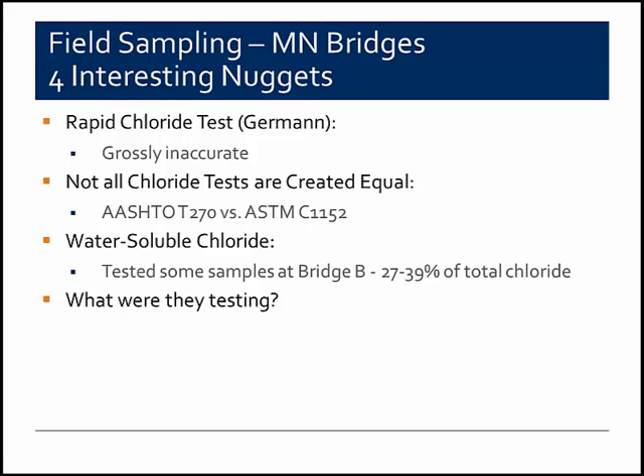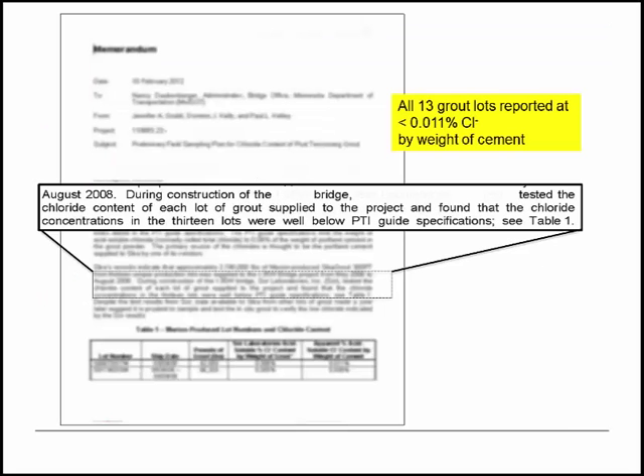And the last nugget is, what were they testing? And that is it with respect to Bridge B, because as Brian mentioned, chloride content testing was not typical during the field or during construction of certain bridges. However, for Bridge B, all 13 of the grout lots that were supplied on that project were shipped off prior to construction for laboratory testing of chloride content to verify the information on the datasheet. And all of the grout lots tested out at negligible chloride content, less than 0.011% by weight of cement. Now, in 2012, we tested 12 of those grout lots, and as the previous slide noted, 86% of them were in excess of 0.08% by weight of cement. So clearly, there's an issue here, whether the data was reported erroneously or perhaps clearly there's a disconnect. What had been reported to have no chloride, in fact, did have chloride.